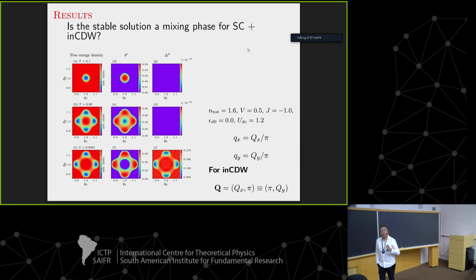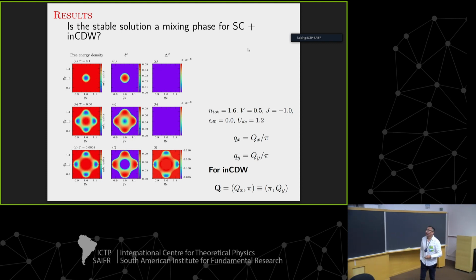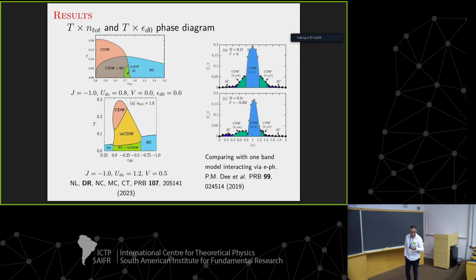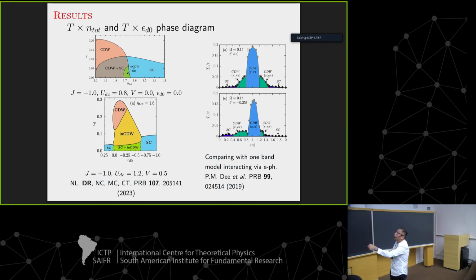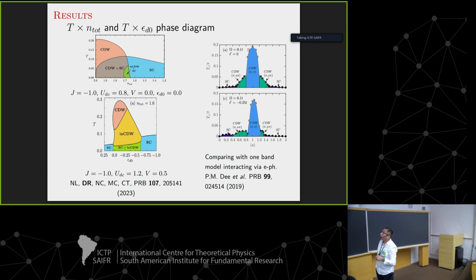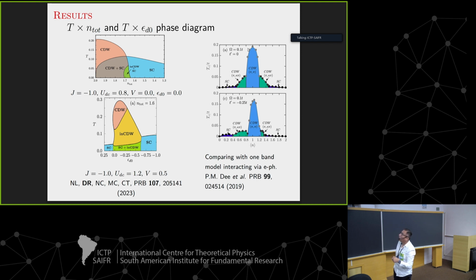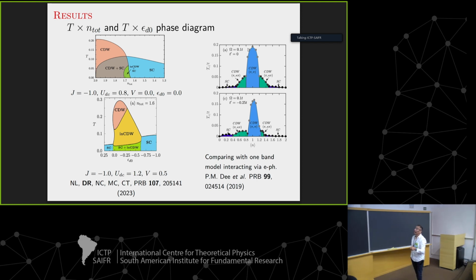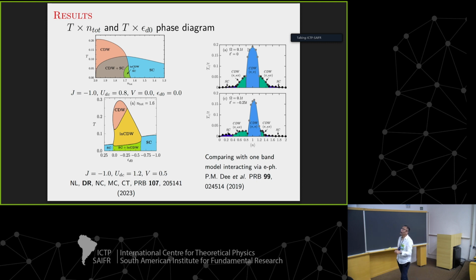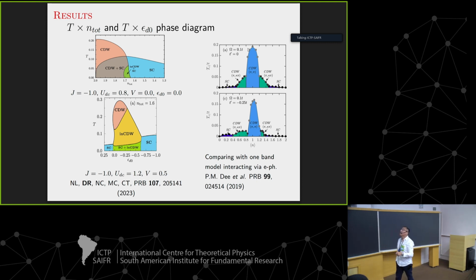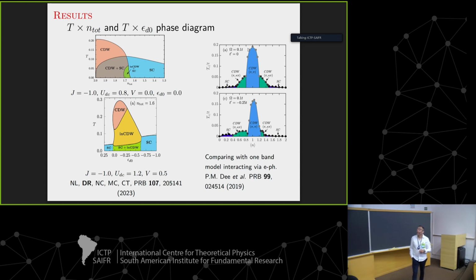The question now is what we can do with all this analysis of the minimum of the free energy. Well, we can construct several phase diagrams. For instance, here we plot the temperature as a function of band filling, and below, the temperature as a function of the relative shift energy between bands. We can observe from both phase diagrams the diverse phases that appear, like incommensurate charge density wave, commensurate charge density wave, superconductivity, and even the coexistence between these phases.